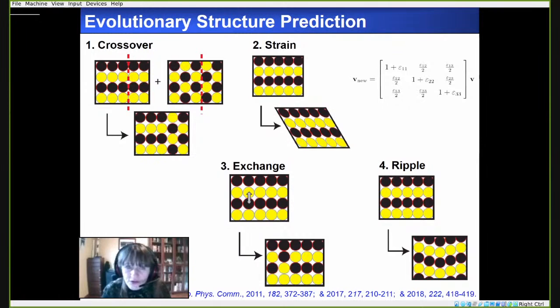And there are a number of methods where we can predict crystal structures. In my group, we use evolutionary algorithms. So the idea of the evolutionary algorithm is that we first produce some sort of random structure or seed a structure with likely prototypes. These structures then go out to our favorite DFT code. They get optimized to the nearest local energy minimum. Afterwards, our algorithm looks to see which structures are the most stable. And then it can take the most stable structures and mutate them in some ways, or take two parent structures and breed them to make a single child structure.